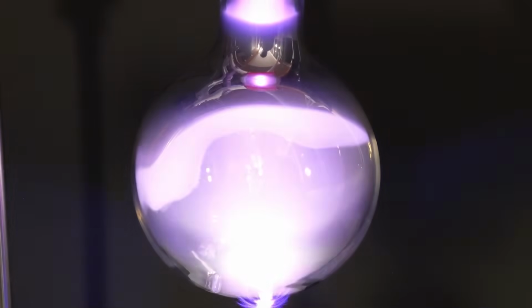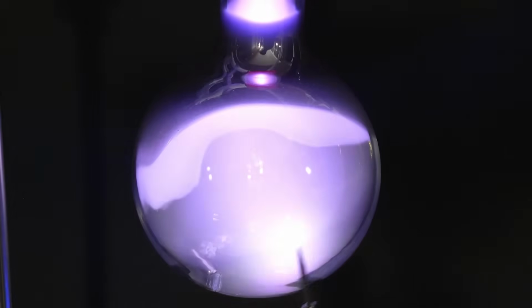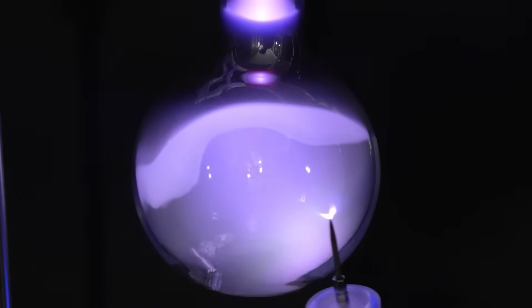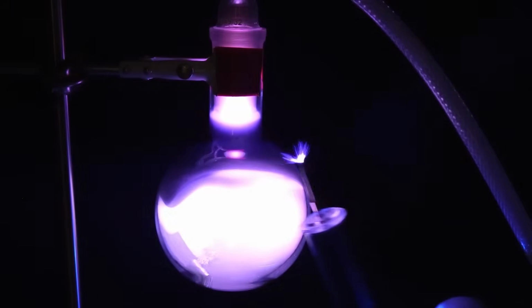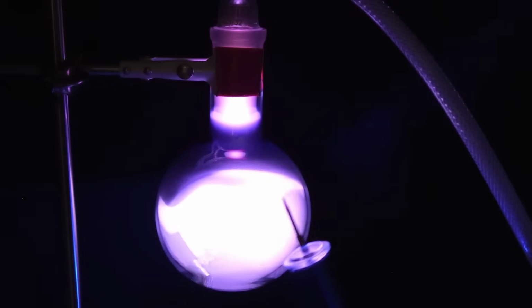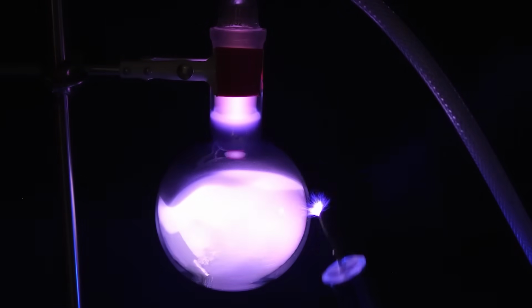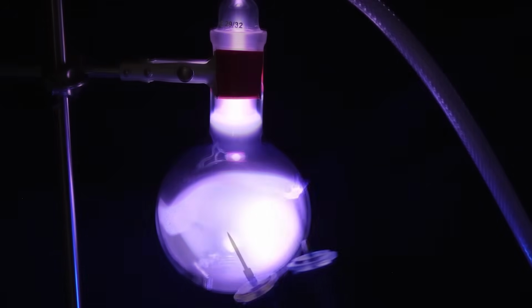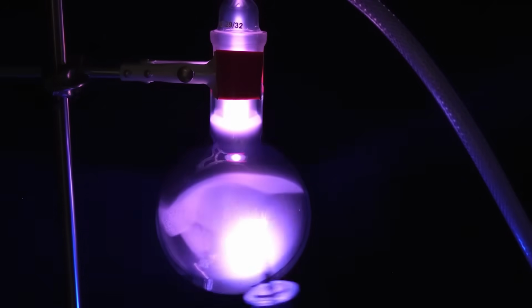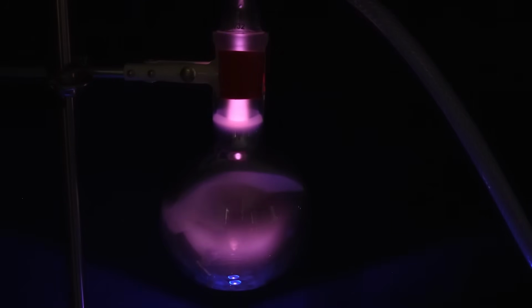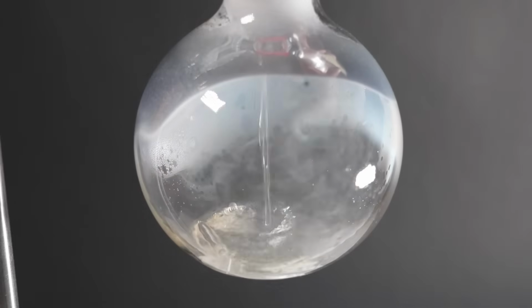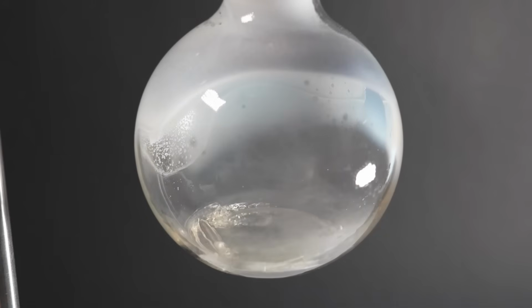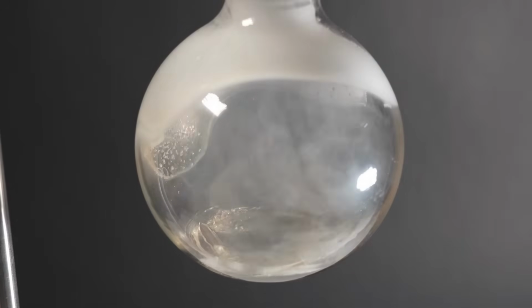Yes, now this is truly beautiful. The resulting potassium plasma has such a beautiful white-violet color. Interestingly, as the flask cooled, the color shifted slightly blue, and when the Tesla coil was removed, it became more pink. It's also interesting that when the flask cooled and I tried to remove the potassium with alcohol, this metal reacted much more actively with ethanol. So, you need to be very careful when conducting experiments with reactive metals.